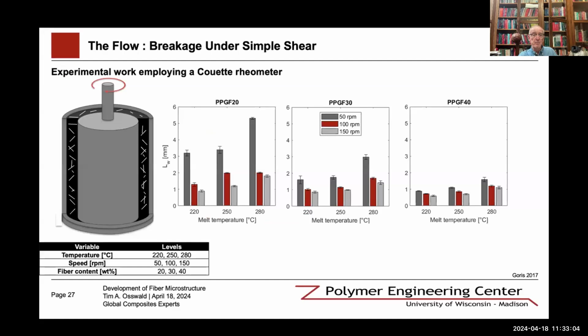So how can we do experimental work to assess what causes fiber attrition or fiber damage? Let's look at, for example, the 20% glass fiber content. That's the graph on the left-hand side. We have 3 colored bars. The gray one is 50 RPM, then 100 RPM, and then 150 RPM of this Couette device on the left-hand side. We built this Couette device where we have a very controlled flow. It's a simple shear flow that can be used to assess the fiber damage and to be able to fit it to models.